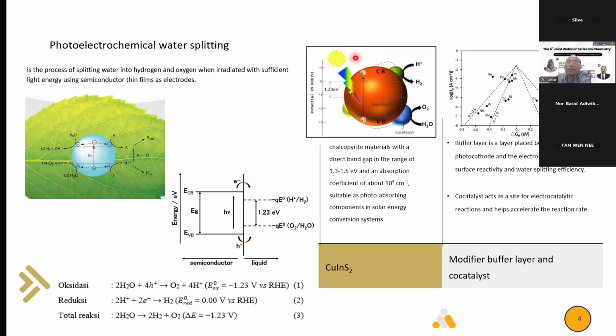And for copper indium sulfide, CuInS2, we call that a chalcopyrite material. Chalcopyrite materials have a direct band gap in the range of 1.3 to 1.5 electron volts, and an absorption coefficient of about 10^5 per centimeter, which is useful as the photo-absorbing component in a solar energy conversion system. Here is an example of chalcopyrite using a catalyst. Usually we use platinum as catalyst. With a band gap of 1.3 to 1.5, it covers visible light, so we can harvest sunlight from UV and visible light.